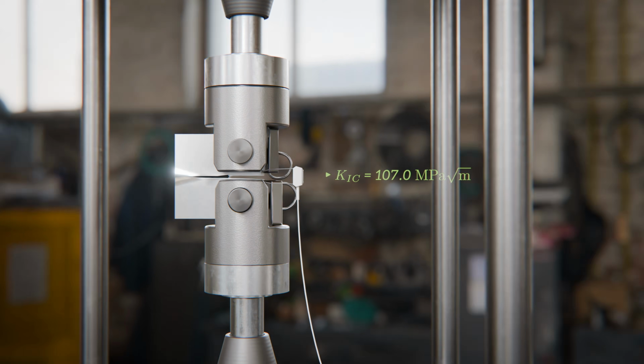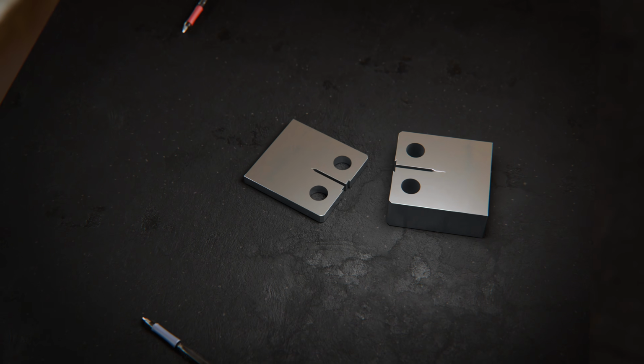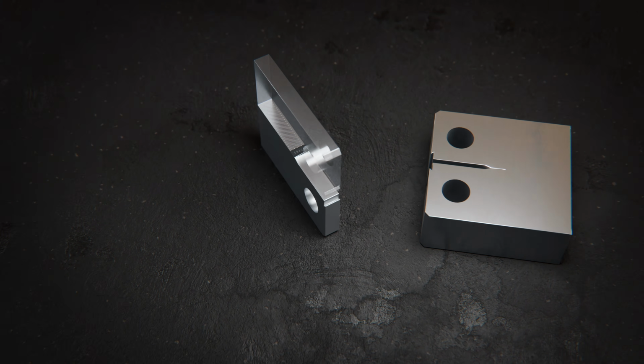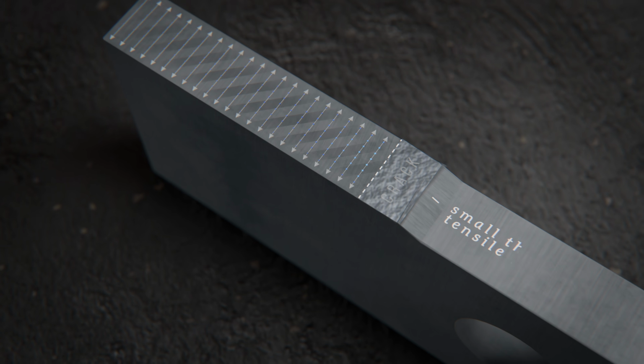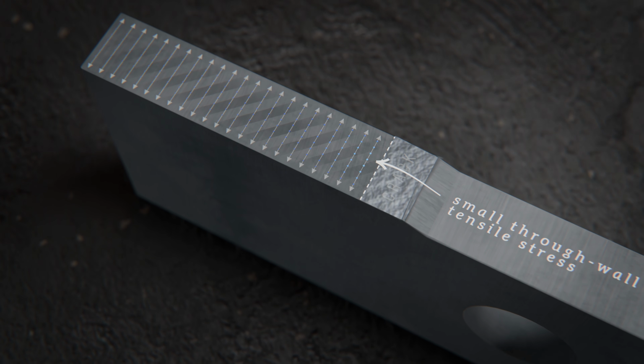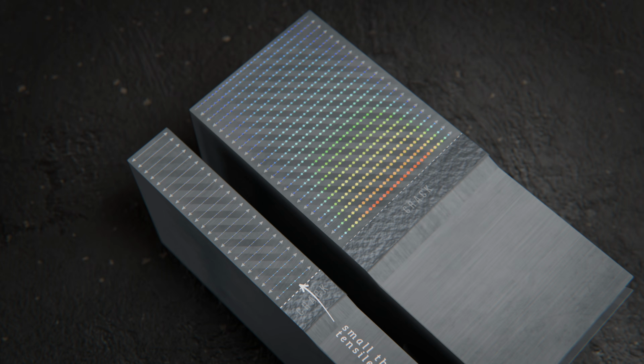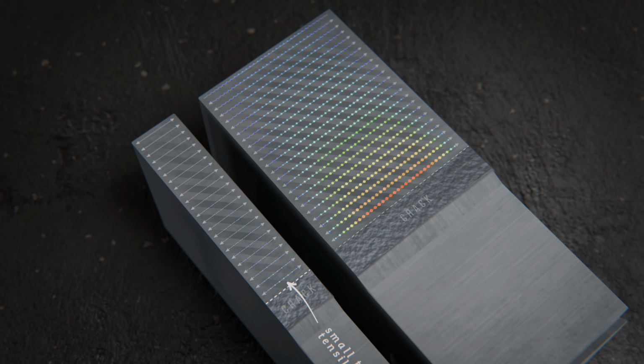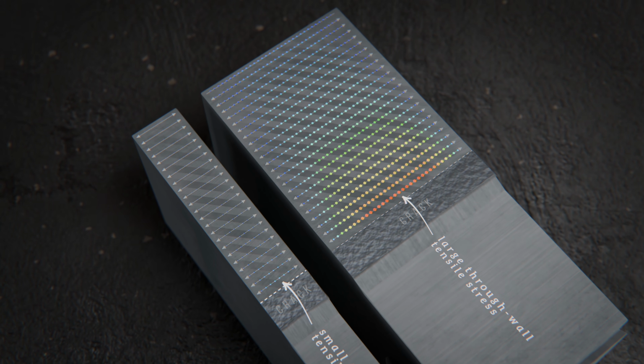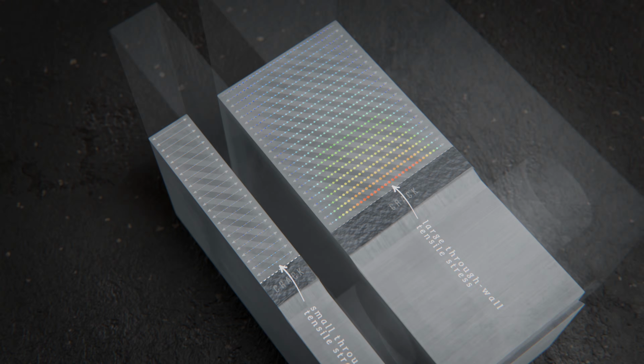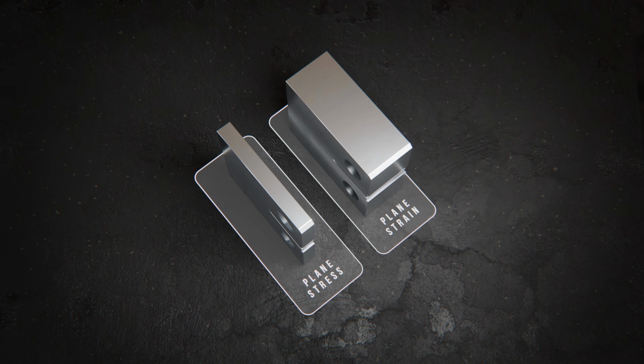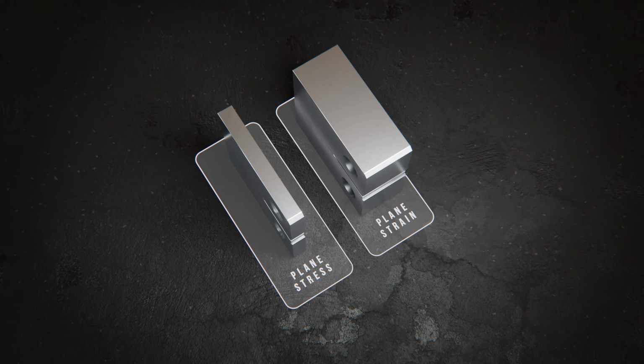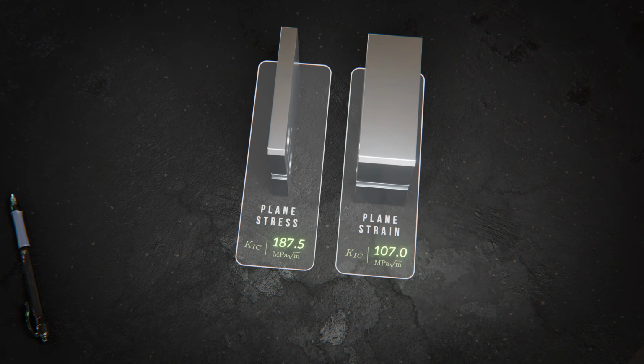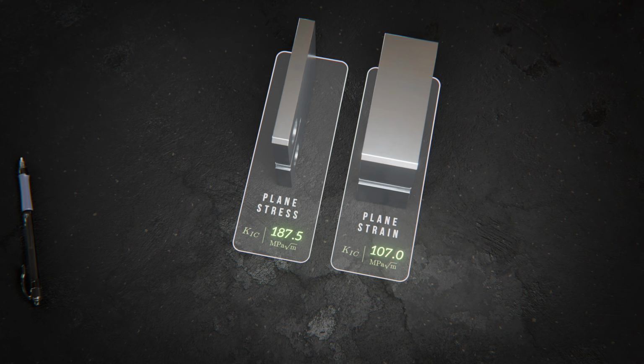The measured fracture toughness depends on the thickness of the material. Thin test pieces don't allow tensile stress to build up through the thickness of the specimen, a condition called plane stress. So they behave quite differently to thicker test pieces, which are in plane strain conditions, where the surrounding material constrains the crack tip and a through-thickness tensile stress develops. The added constraint suppresses plastic deformation at the crack tip, so the material behaves in a more brittle way and shows a lower fracture toughness. For this reason, the standardized test specifies a minimum specimen thickness, ensuring it measures the lowest, most conservative value, corresponding to plane strain conditions.